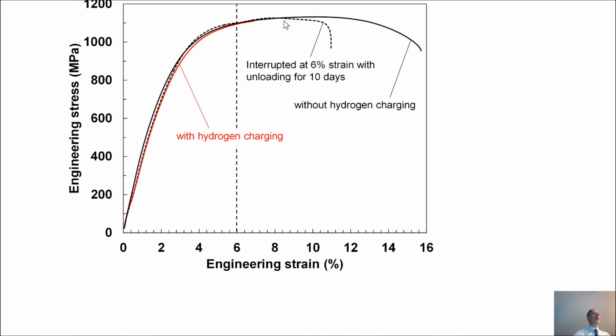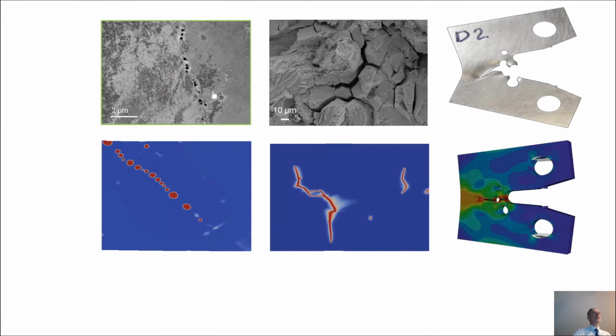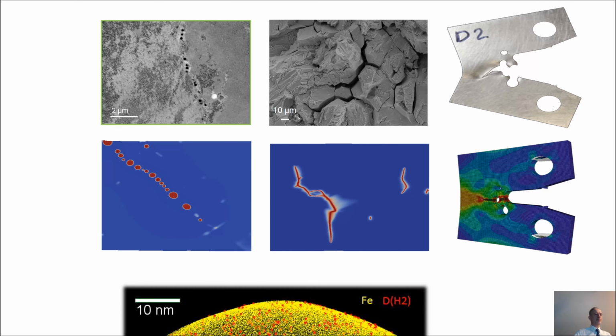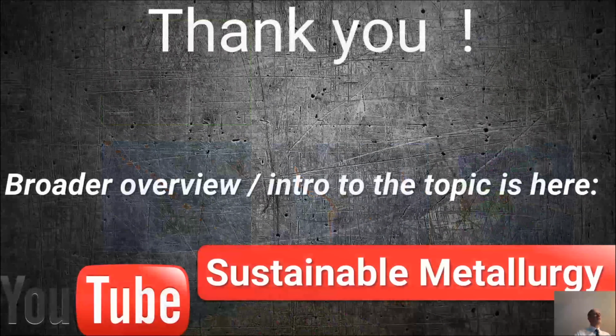This is shown in this type of curve. And these curves are often published in the literature, which simply show that when you expose a material to a high content of hydrogen charging, then you get the so-called hydrogen embrittlement, which becomes visible in a reduced tensile ductility. And it is of course also the target to better understand pore formation due to hydrogen in solid-state iron and decohesion, which are both mechanisms that contribute to hydrogen-enhanced damage. And the task is here, like said before, that we also want to study these effects in the freshly produced iron due to hydrogen in the as-reduced state down to the atomic scale and with theoretical understanding. This is just a projection of what kind of research has to come here in the future.